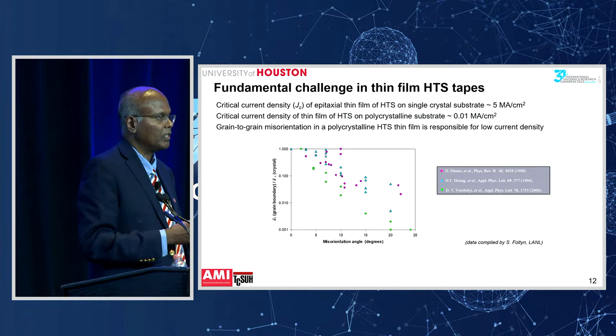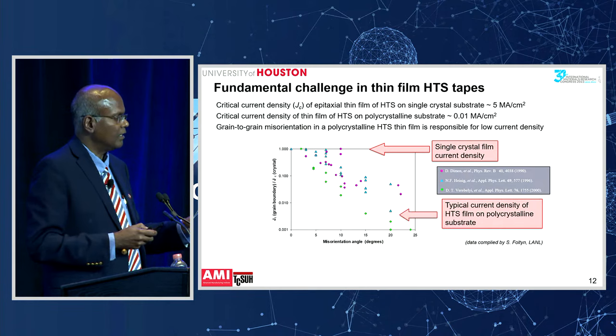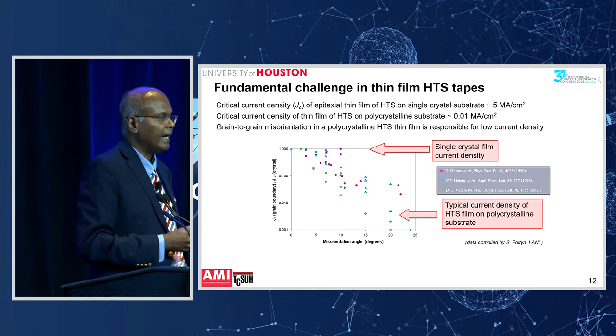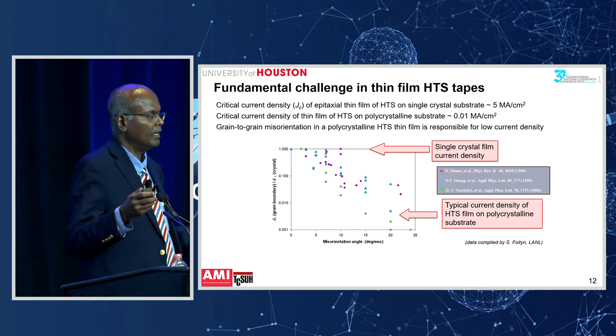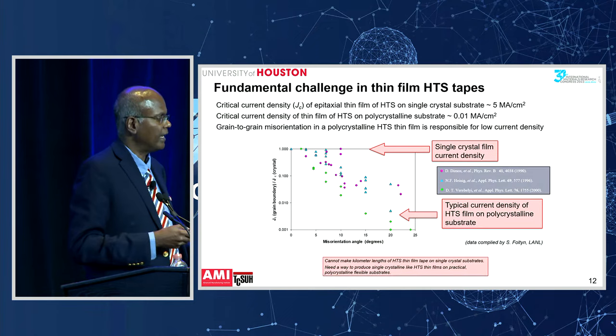So obviously, in a single crystal film, you can get really good performance. But in a typical polycrystalline film, you can see the current carrying capacity is very low. And that was a challenge. So if you try to make these superconducting tapes as a coating on a polycrystalline substrate, it cannot carry much current.